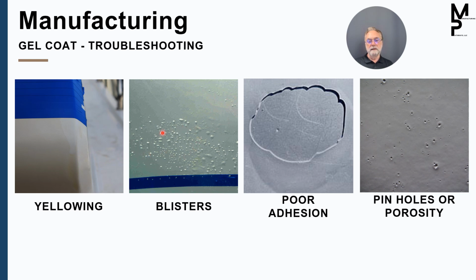Okay, blistering. If we don't get all the air out, or we don't use a good quality resin behind the gel coat, we can get what's called blistering. Water still goes through gel coat at a molecular level. The resin that we use up against the gel coat needs to be a high quality resin. If it's not, that water can attack the gel coat, and then it starts breaking down the resin, and then you get these blisters. These were a big plague in the industry in the 90s, and for a large part we solved that with specialized skin coat resins. We'll talk about that more.